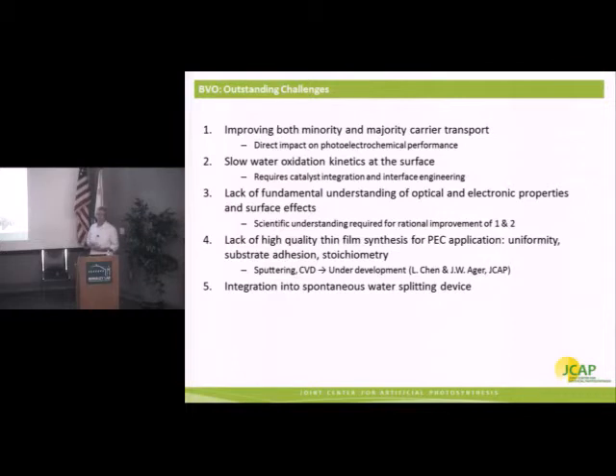It's not very catalytic, so it's not very good at oxidizing water. However, if you apply a catalyst to the surface and do it with care so that the interface is maintained to be of high quality, it can be a very good photoelectrode for water oxidation.